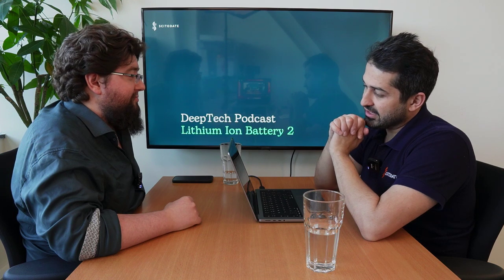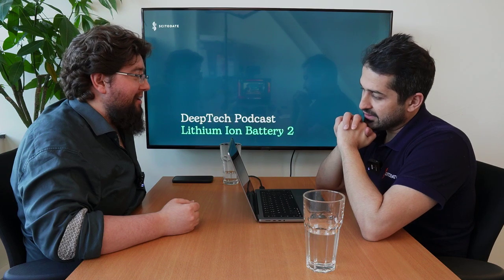So you switch some of the cobalt with titanium or aluminum. So you have, essentially, two different lattices. The image that comes to my mind is reinforced concrete. Yes, you put some wires of aluminum or titanium in the middle of the cathode so that it stays stable.